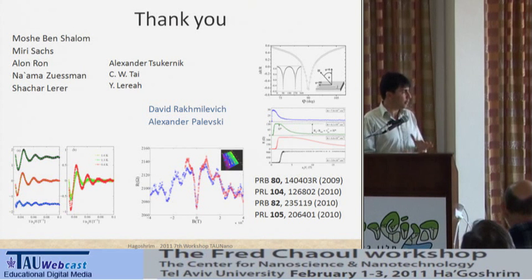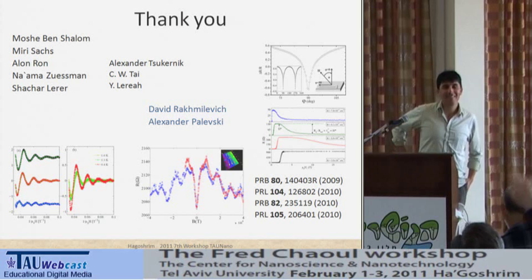So the gate voltage determines the number of charge carriers. It's like a capacitor. So if you change the voltage, you change the number of carriers in each plate. So also the thickness has an effect, but basically it's a 2D system. So the LAO layer doesn't play a major role. It's just the interface between this lanthanum aluminate and the strontium titanate. This is the conducting layer, and superconducting. And magnetic. And magnetic, maybe.